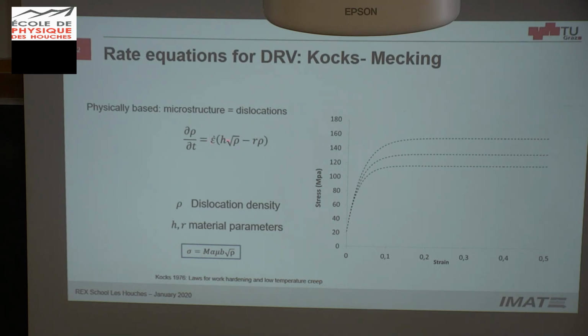The second thing is that H and R are usually fitting parameters. They can be correlated to the temperature in an Arrhenius type, phenomenologically, and to the strain rate in a power law with the strain rate sensitivity. But in any case, you need to adjust them, and there is nothing related to what is happening to dislocations or the interaction of dislocations.